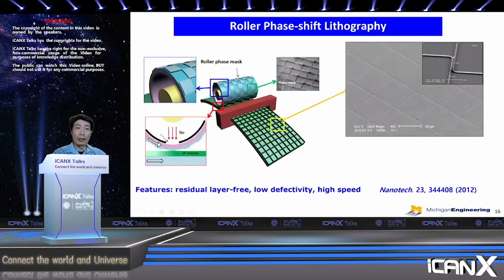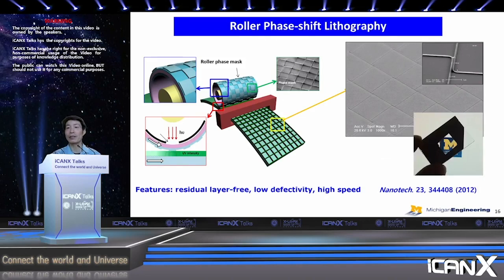Now, you use a quartz tube, transparent to UV light, and you can put your light source inside. And you make your mask surrounding the tube. In this case, it's a phase shift mask, which means it's totally transparent, nothing blocking the light. It only has depth contrast. But the edge of the depth steps can give rise to an optical phase shift and interference. You can have destructive interference, for instance. Then you can make very tiny features, even if the pattern square is, let's say, 10 micron. You can go down to a couple hundred nanometers.